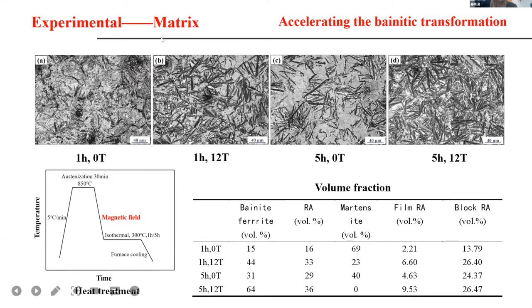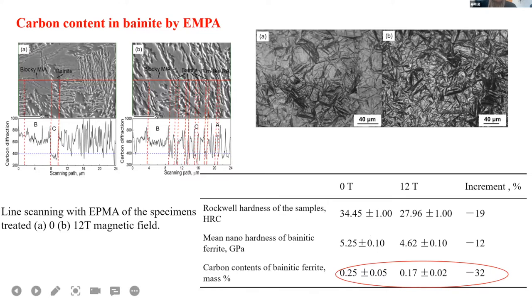The first is about the acceleration of bainitic transformation. Under a magnetic field of about 12 Tesla, the bainite volume fraction increased. This table shows the bainitic ferrite volume fraction without the magnetic field is about 15, and under the magnetic field, it increased to 44. So that means the magnetic field promotes the bainitic transformation.